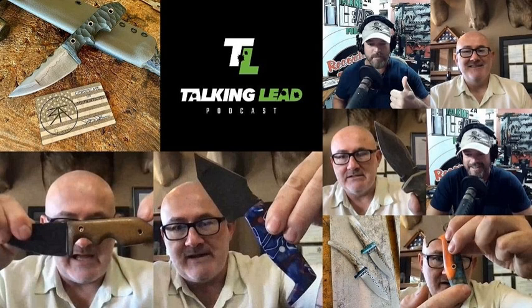The nice thing about a hollow grind is, when you're talking about a knife like a kukri, I do a hollow grind on the kukri as well. Part of the reason is I have this much blade up here and this much handle, so I'm looking at being blade heavy. It wants to go forward because it's a chopper, but it's also a fighter. People don't realize that a kukri is meant for stabbing. If you look at the way a kukri is shaped, it's the perfect stabbing weapon because instead of going straight, it angles out. If I'm stabbing something that's not angled, my wrist has to be like this. With the angle, I can bring it down almost like I'm shooting a pistol. By being able to go into that deep hollow grind, I'm taking weight off the blade.